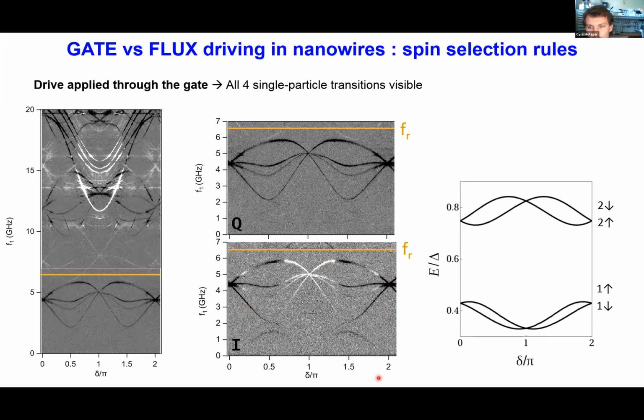And so in this case, it's very different from the simple nanowire spectrum that I presented before, where the shift was mainly due to the curvature. Here, the situation is very likely to be much more complex because the transitions, as you can see, are very close to the resonator. So both the curvature and all the virtual transitions between Andreev levels contribute. And so for some given values of the flux, it is possible that the energy of virtual transitions match the frequency of the resonator, and this is what gives all this change of colors here.